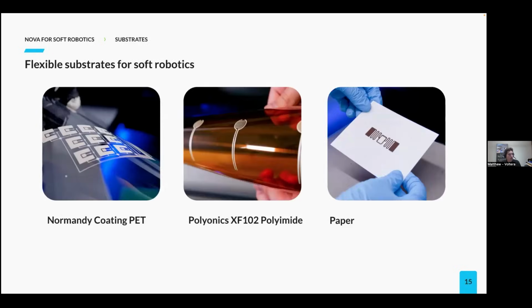Moving on to our substrates, let's touch on some flexible substrates that you can use on Nova. So we have specifically Normandy's PET. PET is a transparent film, and this one is engineered for precision material deposition in flexible electronics. It's heat stabilized, so this minimizes shrinkage and ensures that the substrate maintains dimensional stability during high temperature curing processes, which is needed for ink. And PET is a very cost-effective material that you can use when you're prototyping your flexible circuitry.